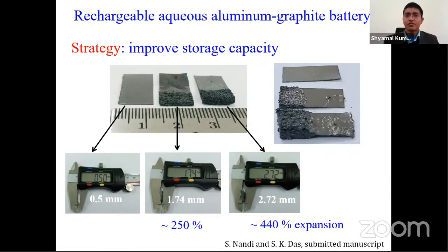We also realized that with expansion of the graphite foil, this is your pristine graphite, if we expand it, then we can improve the capacity. Now, can we expand it more? We could increase up to 250%. Can we increase it more? Yes. Now we have found the technique. That manuscript is submitted and under review. It is a technique by which we could expand the graphite foil up to 440%.